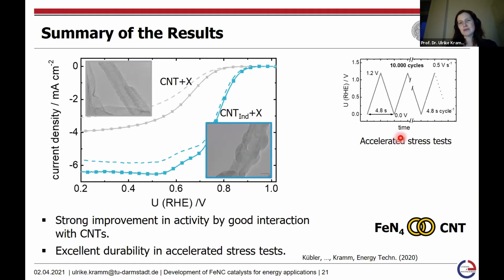In this case, this was 10,000 cycles in a potential window between 0 volt and 1.2 volt, which is quite a lot. And what you can see is that even after this accelerated stress test, the modified catalyst material functionalized with indazole prior to the heat treatment gave a very good durability in comparison to the non-functionalized CNTs used within the synthesis.